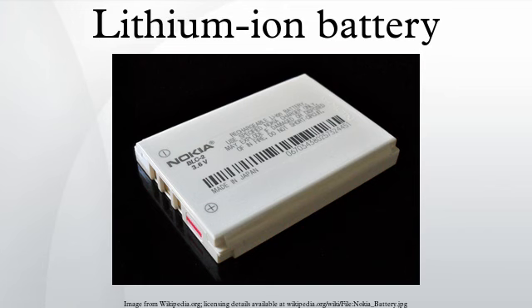Although a battery pack may appear to be charging normally, electroplating of metallic lithium can occur at the negative electrode during a sub-freezing charge, and may not be removable even by repeated cycling. Most devices equipped with Li-ion batteries do not allow charging outside of 0-45 degrees Celsius for safety reasons, except for mobile phones that may allow some degree of charging when they detect an emergency call in progress.